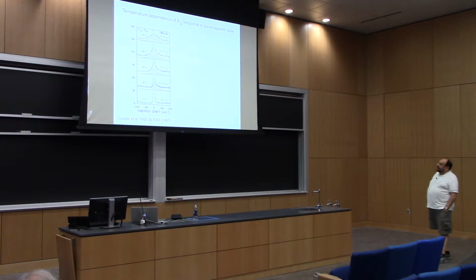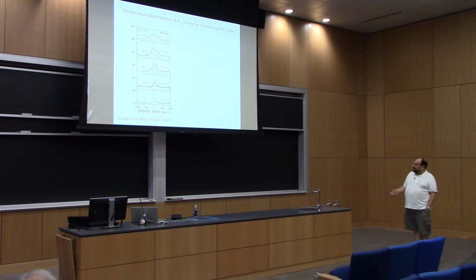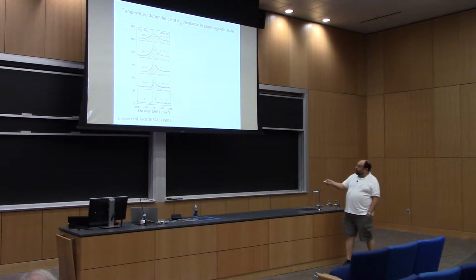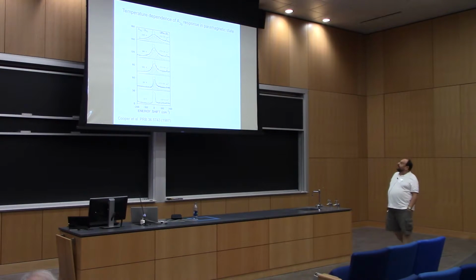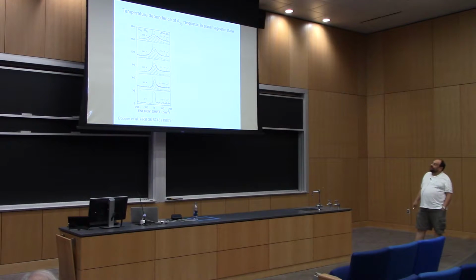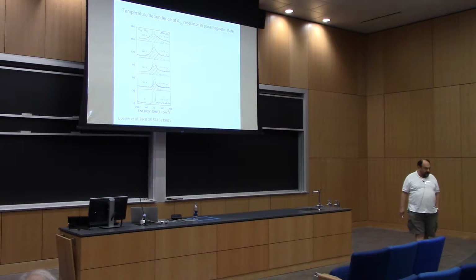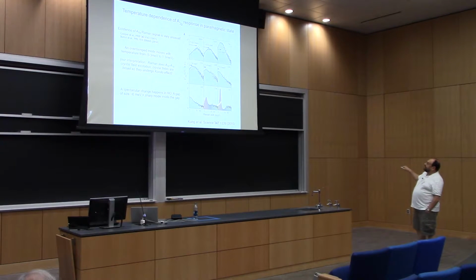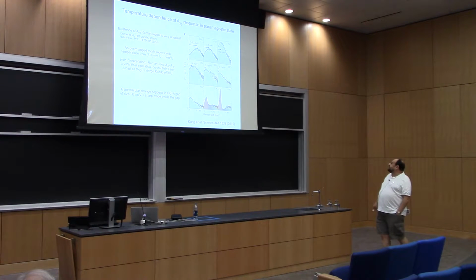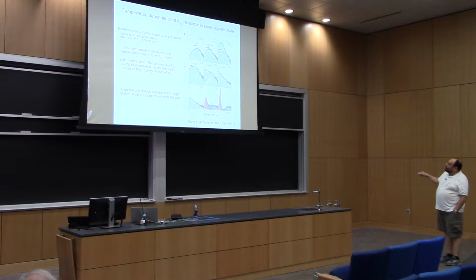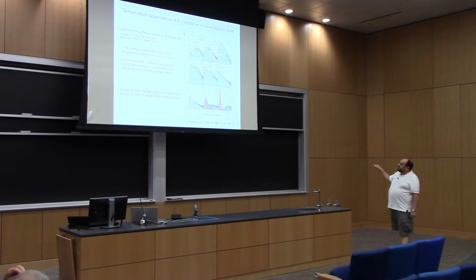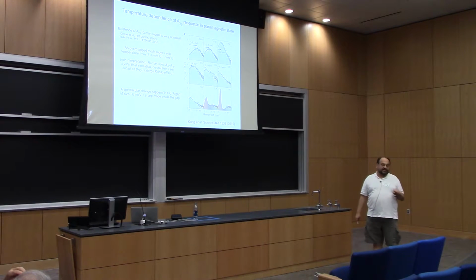The experiment is Raman scattering, again, that was introduced in the previous talk. I repeat the transparency from the paper of '87, where on Brian's sample, Lance Cooper, who was then a student at Urbana with Miles Klein, did these measurements, and already then they identified that in the paramagnetic phase, the fluctuations are in the A2G channel, right? And this is the more fine work that both we did in New Jersey and also in Paris, essentially showing that there is a strong signal, this is a semi-log plot, Raman response function versus Raman shift. There is a strong signal only in the A2G channel. Other channels really don't have much except phonons.